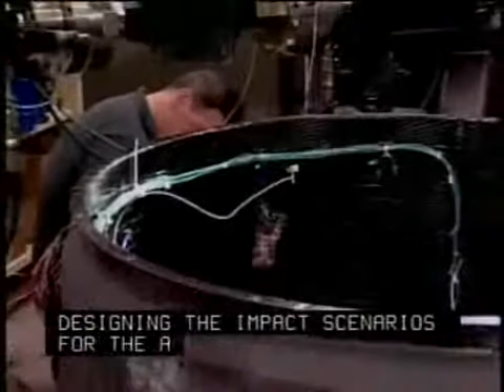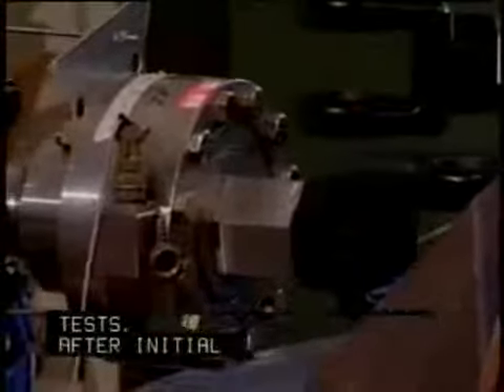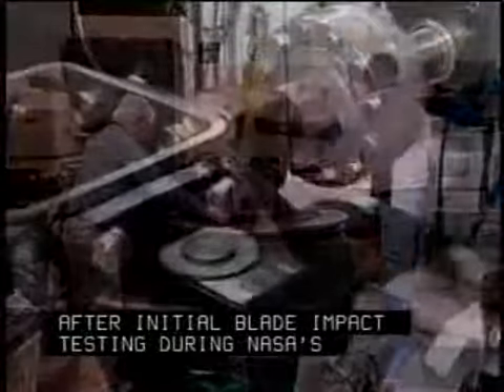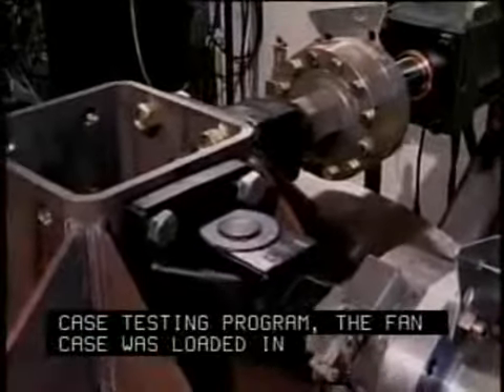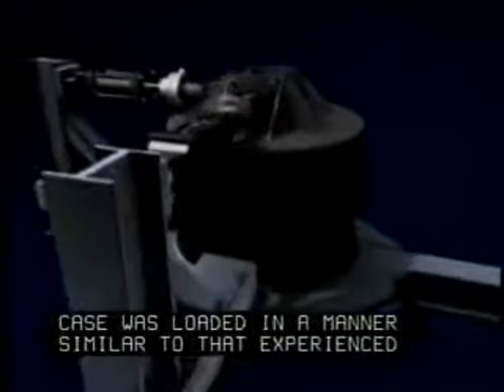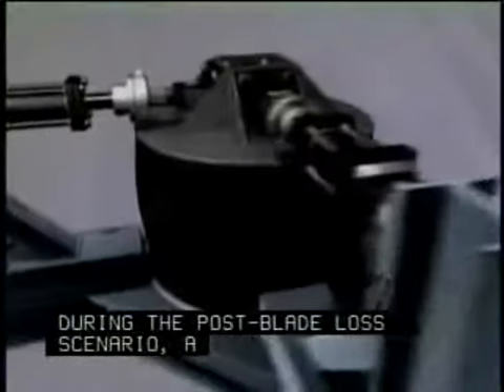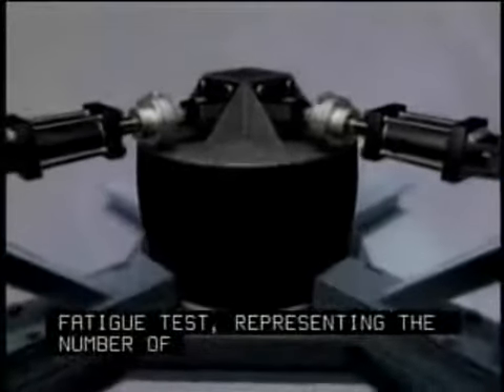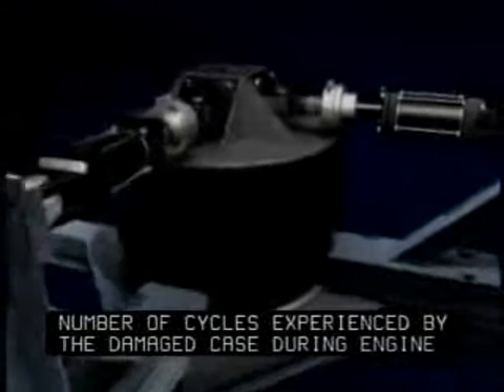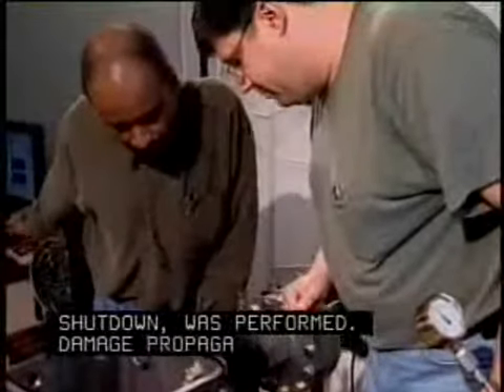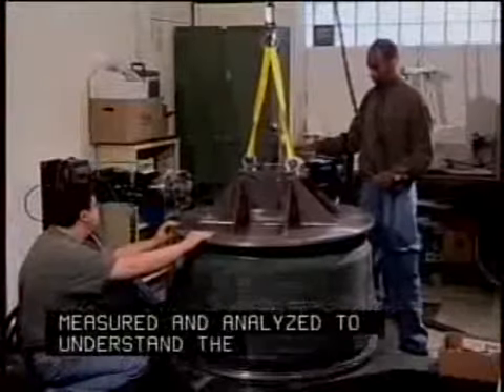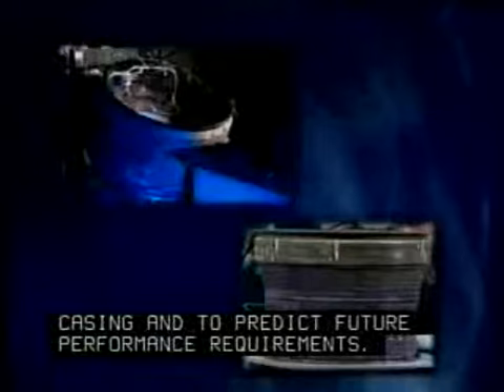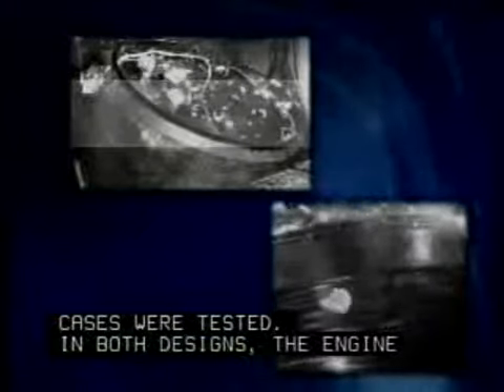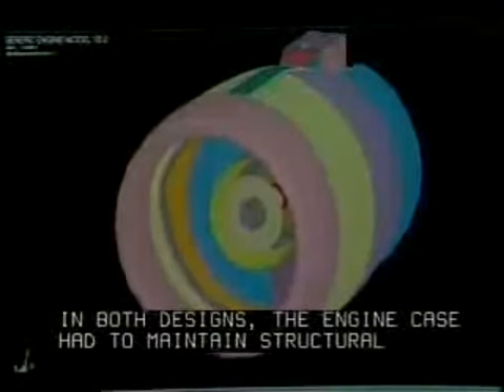After initial blade impact testing during NASA's full-size case testing program, the fan case was loaded in a manner similar to that experienced during the post-blade loss scenario. A cyclic orbit fatigue test, representing the number of cycles experienced by the damaged case during engine shutdown, was performed. Damage propagation was then measured and analyzed to understand the success or failure of the containment casing and to predict future performance requirements. Both softwall and hardwall fan cases were tested. In both designs, the engine case had to maintain structural integrity after impact and withstand the rigorous loads imposed by an out-of-balance rotor.